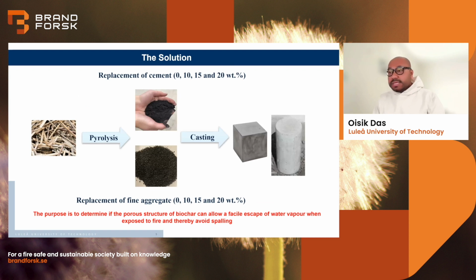So how are we using biochar in concrete? We are replacing both cement and aggregate. By replacing cement, we can make concrete less polluting and reduce the carbon footprint. And by replacing aggregate, we can upscale or valorize food waste. So from pyrolysis of biomass waste, we are making the biochar. Here we are using two types of biochar: a fine biochar, with small particles, and a coarse biochar, with bigger particles. The fine biochar is used to replace cement at 10, 15, and 20 weight percent of the cement. And the coarse particles of biochar are used to replace the fine aggregates at the same weight percentages of the